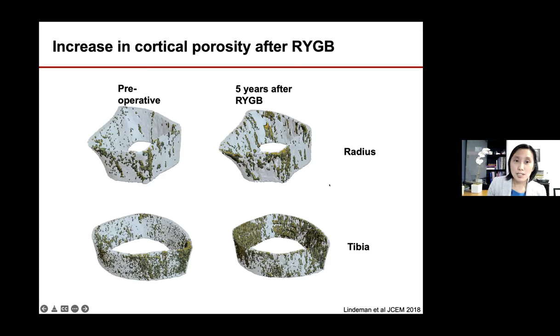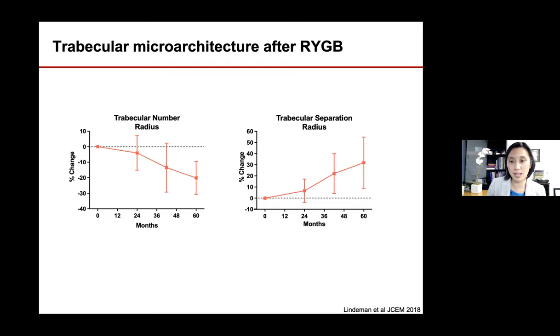Here you see a visual representation of cortical porosity after gastric bypass. Here you have the cortical shell, which has been divorced from the inner trabecular core. And the cortical pores are shown here in this yellow-green color. And you can see the great increase in cortical porosity at both the radius and the tibia in the 5 years after gastric bypass. This is just using the standard measures of cortical porosity and not necessarily the specialized laminar analysis that Dr. Kazakia had presented in her earlier talk. Nevertheless, you can see that this may potentially have an important impact on skeletal strength.